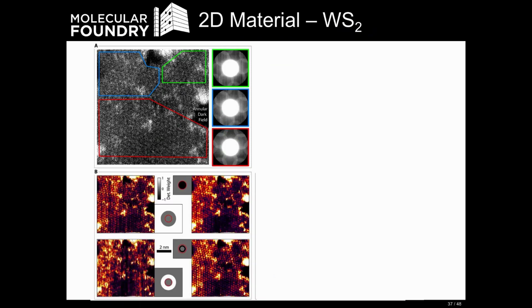So a couple simple ones first on the lower left. If I make a virtual bright field where I flip the contrast, that's the upper right of that panel, or a bright field where I extend beyond the center disk. The center disk is labeled in red there. I can form some clean atomic resolution images showing the tungsten sites of this lattice. Or I can show annular dark field in the lower left or annular bright field in the lower right. If you look really closely, the annular bright field in the lower right of this panel is much cleaner than the other two atomic resolution images. So this shows the real power of virtual dark field imaging. You don't have to set your detector inner angle and your detector outer angle before you do the experiment. You can do it in post-processing after to form the best possible quality image.